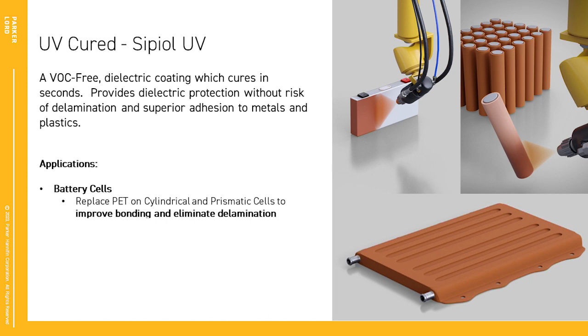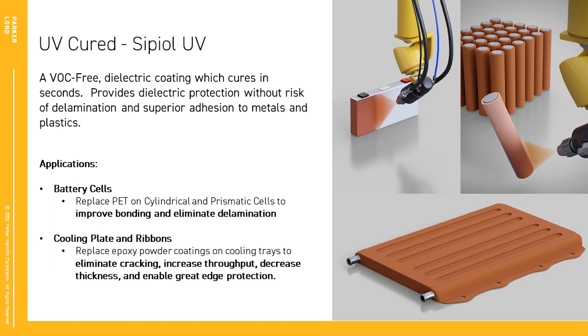Sipiol UV was formulated specifically to have good edge coverage all the way down to a 0.03 millimeter radius. So very sharp edges can still be coated quite effectively with Sipiol UV. In addition to coating individual cells, Sipiol UV can be used on cooling plates to replace thick powder coating. So long as there's direct line of sight to UV light, Sipiol UV can be used anywhere that you want to use it for dielectric protection. This could essentially take a potential powder coating process, which generally takes about 40 minutes with ovens, to under a minute with just UV light. It's a very compelling technology.